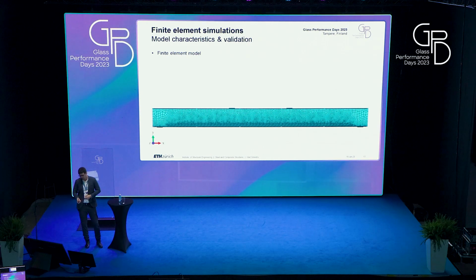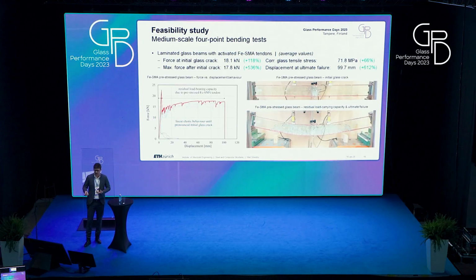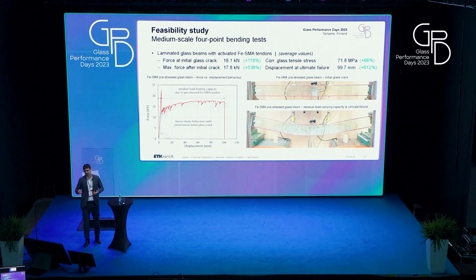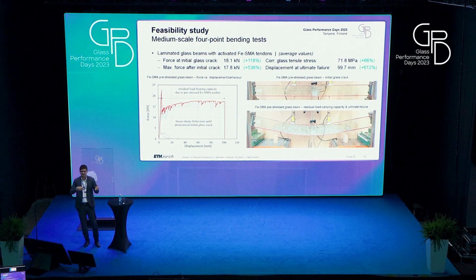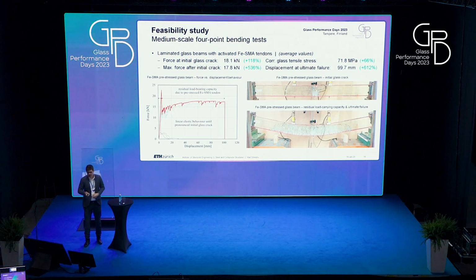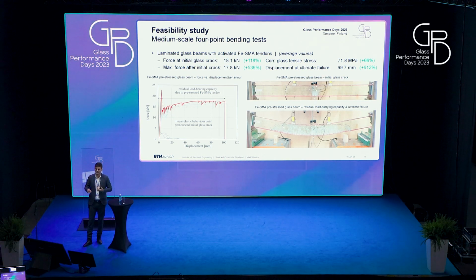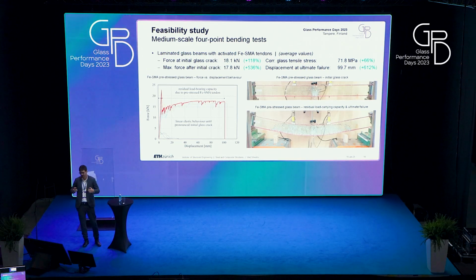So to conclude about the tests, this showed that the concept we introduced works well. We didn't see any negative influence of the adhesive because it was heated in the middle part before the test. During activation, we saw very locally some delamination. So we thought it would be nice to also look at some different concepts, maybe without adhesive, or adhesive just in the anchorage part.